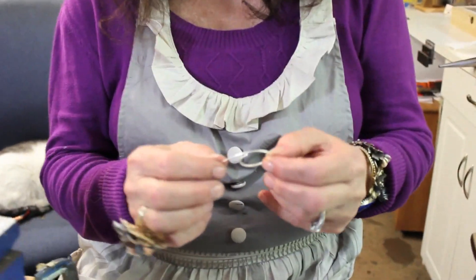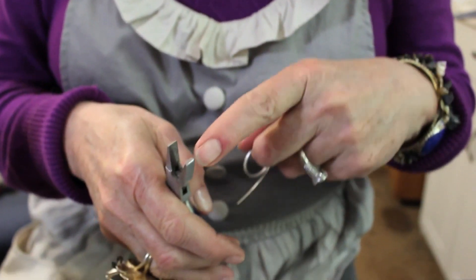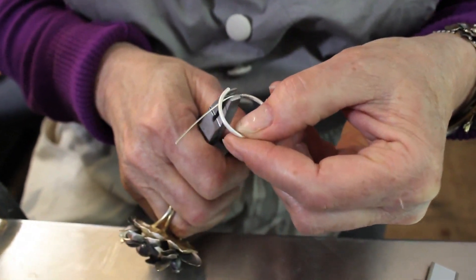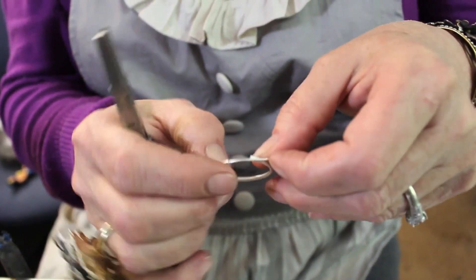The wire's in there now. We want this ear wire to follow the natural curve of the piece. I'm using a plier that's got a rounded edge on one side and a square on the other, and I'm just going to shape it a little bit. One thing I want to say about making this hollow tubing earring — you should probably boil it in baking soda, because the pickle gets inside. Or run a thin stream of water down in here to rinse it out thoroughly. And move this back and forth — it's not a bad idea to work-harden it, because that soldering process annealed this.